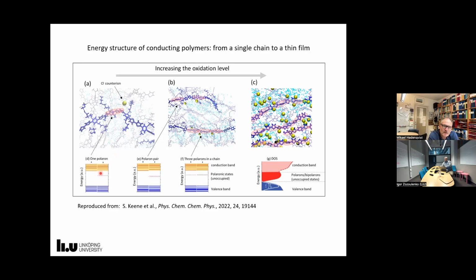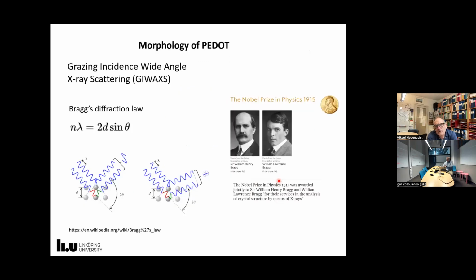And then there is this state, polaronic state in the gap. So here in this case, you add more and more charges. So here, for example, when you have 3 states or more, you have more and more polarons. And finally, in the fully charged, fully oxidized system, you have a lot of these polarons, a lot of counter ions, and these polarons form a so-called polaronic band inside the gap between the valence band and the conduction band. Okay, so now what is the morphology of this system?